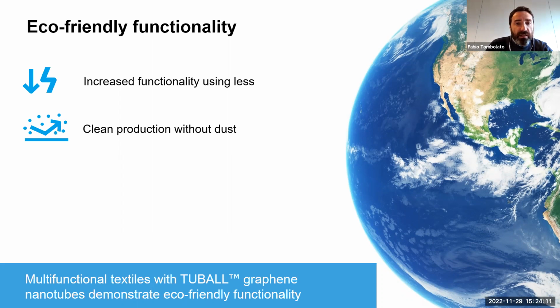Clean production without dust. OCSiAl has developed a full range of master batches and solution concentrate that help the customer to manage graphene nanotubes in a very clean production without dust. Low working dosage, high efficiency, clean production thanks to the use of master batches, and a very efficient logistic all contribute to reduce the emission accounted for the product production.